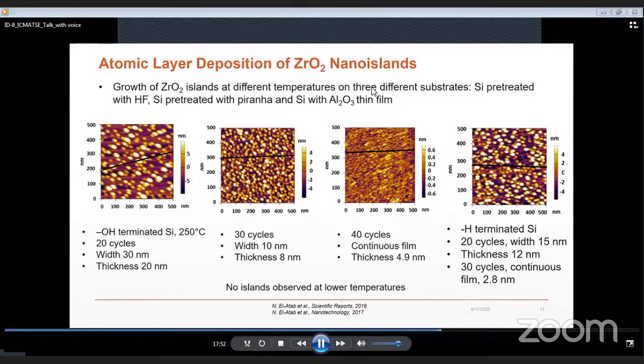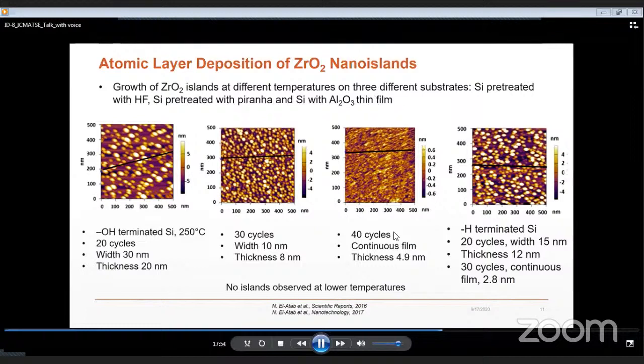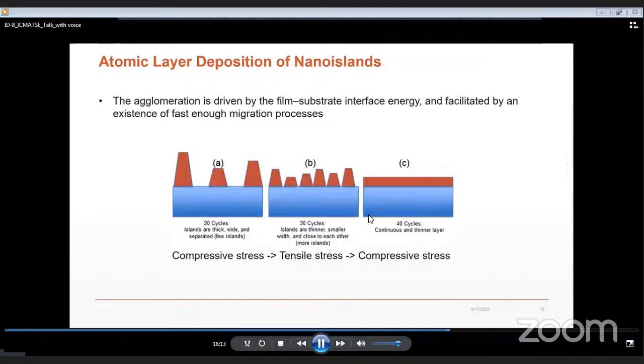It's worth mentioning that no islands were obtained at lower deposition temperatures of 150 and 200 degrees Celsius, which confirms that when the temperature of the substrate is sufficiently high, the adsorbed atoms gain the needed energy to diffuse on the surface and agglomerate to minimize the entire energy of the system. The growth mechanism can be explained by considering the thermodynamic tendency of a full system to reduce its total energy. Surface atoms are bound less tightly and therefore are more energetic than the bulk atoms in a specific structure. This surface free energy tends to be lowered when the surface area is reduced. As a result, the layer reduces its surface free energy by balling up into a 3D island.